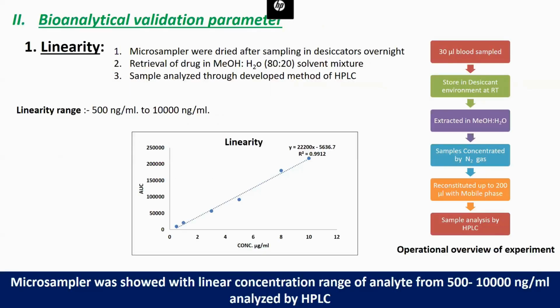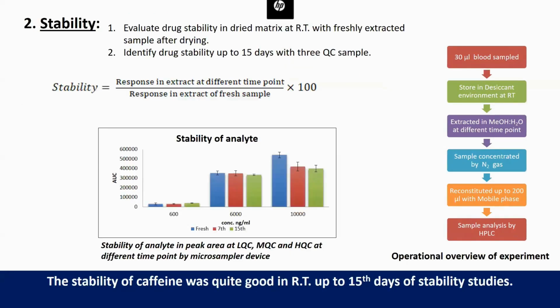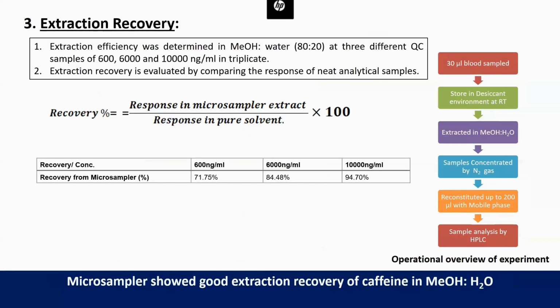Further, we checked the linearity for the different samples, and we found that for varying concentrations in the 2 to 12 range, the extraction procedure was quite linear in nature. Then we checked the stability of the analyte, because the analyte needs to be stored and transported and then extracted. So how long could it be stored? From the fresh sample to the sample collected at 15 days, we were able to see that the stability was quite good. And finally, the extraction recovery. After being stored for a long period of time, can we extract the amount? When the concentration is high, like 10,000 nanogram per ml, we were getting 95% recovery, whereas at 600 nanogram per ml, we were getting only 71%. This data is good enough to start with.